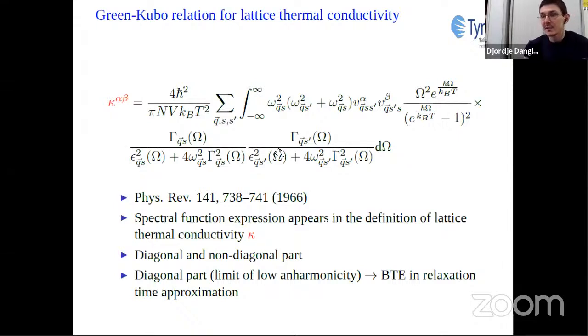The first part is diagonal in phonon branches, which is the traditional definition of the heat current. And the second term is non-diagonal in the phonon branches. One can show that the diagonal part, so when S is equal to S', in the limit of low anharmonicity, that means that the imaginary part of the self-energy is much smaller than the phonon harmonic frequency, and the real part of the self-energy is zero, this expression reduces to the Boltzmann transport equation in the relaxation time approximation.